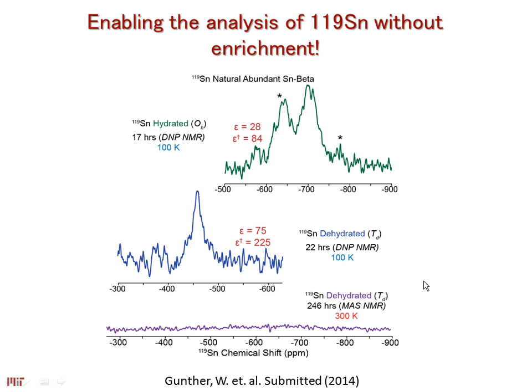Another big issue is, as I told you, this framework incorporation of tin centers is very critical for us to understand reactivity. And a big bottleneck in investigating these materials with NMR is that if you want to do tin NMR, you have to enrich the sample. You always have to buy an enriched precursor like tin chloride. And the last quote that we got, for example, from Cambridge Isotope was that for a gram of this tin chloride, you have to pay about $12,000. It's extremely expensive, and it really limits your ability to perform your NMR experiments and really figure out what is happening over there.